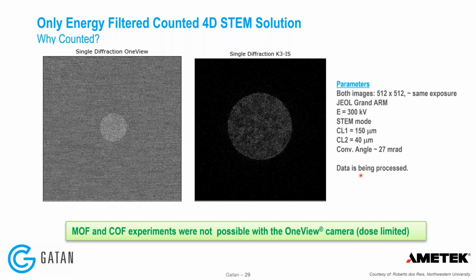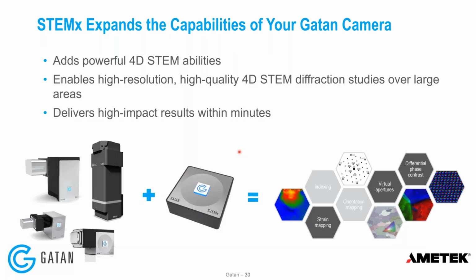And lastly, but of course not the least, and this is also one of the most important advantages, is that you can do electron counted diffraction imaging with Gatan cameras. So here is showing the difference between diffraction images collected on a OneView camera, which is a scintillator charge accumulating detector, versus a K3 IS camera, which is a direct detection electron counting camera. Exact same conditions on the sample, exact same microscope conditions and exposure. You can see the difference in the signal to noise ratio between the two detectors. And then, right, so this is what I wanted to talk about on 4D STEM and STEMx.